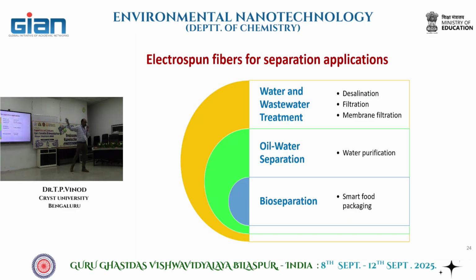And then the second set of applications electrospun membranes can have is for separation, because you have a membrane of very controlled porosity through which materials can pass, and which material can pass through it you can decide by controlling the porosity of it. How to control the porosity? You actually change the deposition time. More deposition means more fibers per unit area, and the porosity is smaller and smaller. So you have absolute control over what can pass through the filter and what cannot pass through the filter in the size parameter.